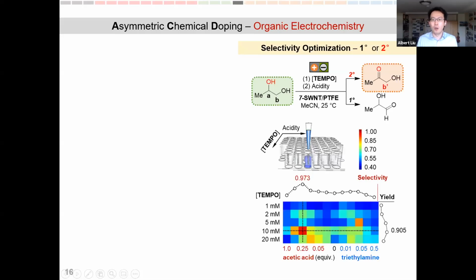With our particle, though, we can do this screening using, again, a 96-well plate where we can just pipette different solvent conditions into the wells that have our particles in them. And in one fell swoop, we can basically identify the condition at which we can generate 90% yield and essentially 100% selectivity towards the secondary alcohol product.